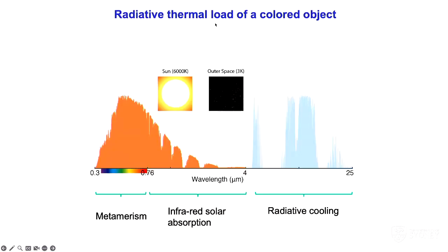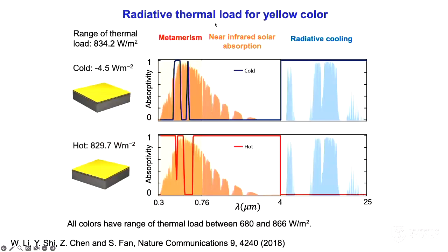So for different spectra, our eye can actually see similar colors. And different spectra will have different power content in the solar part. Taking all these factors into account, Wei Li, who is sitting there, who was a postdoc then and is now a professor at the Chinese Academy of Sciences, did this calculation where he looked at a yellow structure, something that looked yellow. But he played with all three effects: the metamerism, the visible spectrum, so two visible spectra can give the same yellow color, the control of near-infrared solar absorption, and the radiative cooling.